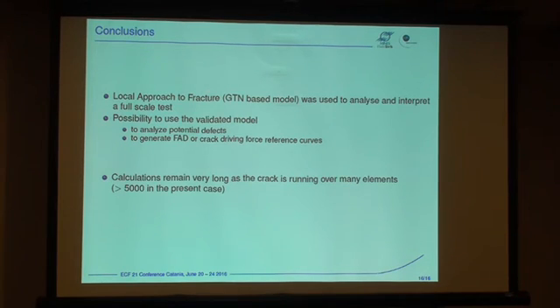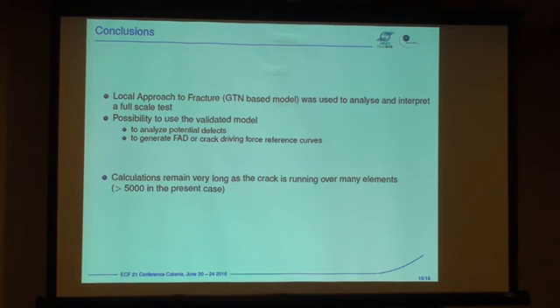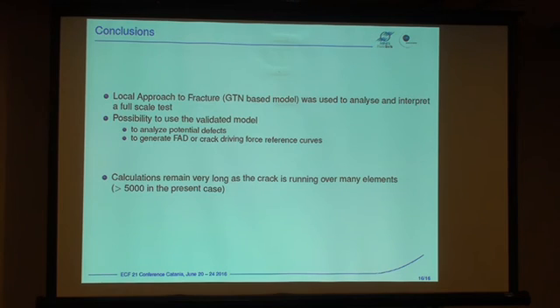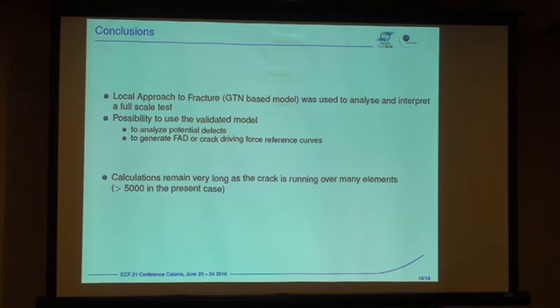In conclusions: the local approach to fracture — in that case the Gurson–Tvergaard–Needleman (GTN) based model — was used to interpret the full-size test. This kind of modeling could possibly be used to analyze potential defects, small or complex defects in pipes. It could also be used to generate failure assessment diagrams and crack driving forces which are used to design pipes. The main drawback is that these calculations are very, very long. The reason is not the number of degrees of freedom — which is high but reasonable — but the fact that many, many elements have had their porosity exceed 5% and been removed before the crack reaches leakage. We are working on improving that kind of simulation.